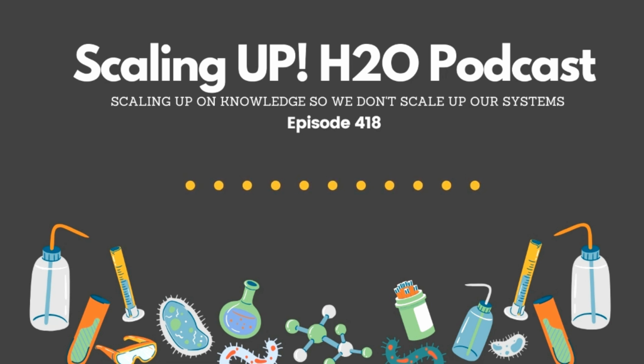It can go either way. You've got to really be careful, because one of the things that people a lot of times don't think about when they're doing lab testing of corrosion inhibitors is making sure that the surface area of the coupons being used versus the water volume is consistent with what you might see out in the field. If you get that right, then your dosage demands can be pretty close. If you get that a little bit out of whack, then you could either underestimate or overestimate how much corrosion inhibitor is necessary. I'll ask water treaters that'll try a new product, and 9 times out of 10, I'll get some sort of sensational reply.